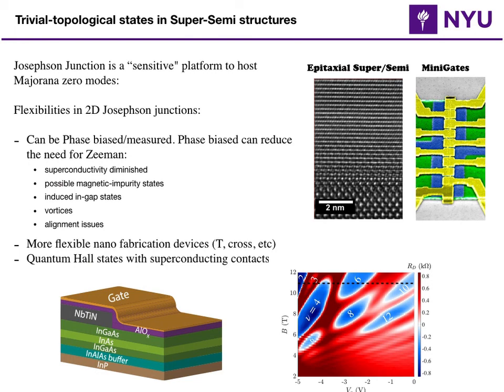So I just want to say that Josephson junctions are a very sensitive platform, and that's good. For example, when we wanted to measure the phase, we could use the SQUID geometry to do this. There's a lot of technology that has already been developed on Josephson junctions, so that allows flexibility in the fabrication. And not only can they be phase measured, they can also be phase biased, as I mentioned, and that reduces the need for the Zeeman effect, right? So we don't need to have 1.2 Tesla critical field, and maybe we can get by with a much smaller magnetic field.